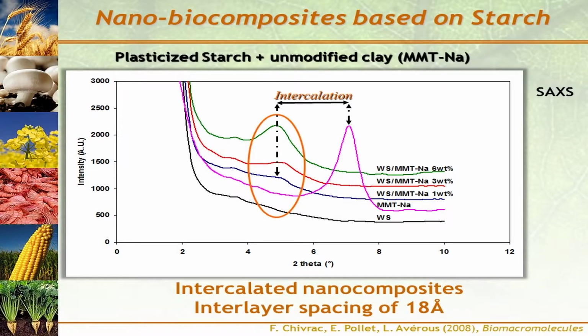So we prepared a nanocomposite based on plasticized starch, first using the so-called unmodified clay, the sodium montmorillonite, and by small angle X-ray scattering, you can see here the typical diffraction peak of the clay in pink due to the regular stacking of the clay platelets. And when you disperse this clay into plasticized starch, you see a shift of this peak, showing that you have intercalated some species between the clay platelets.